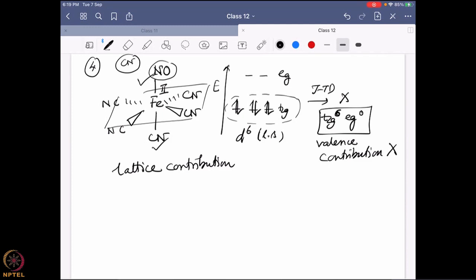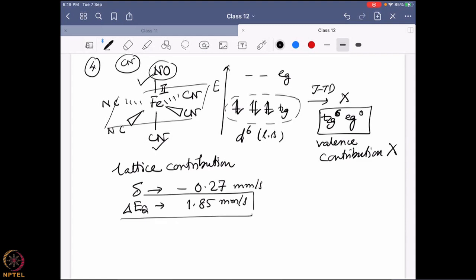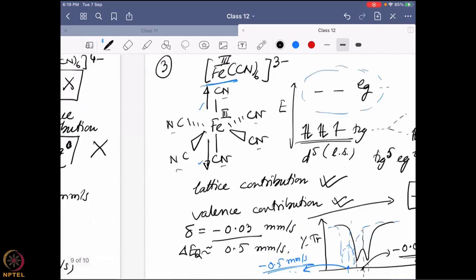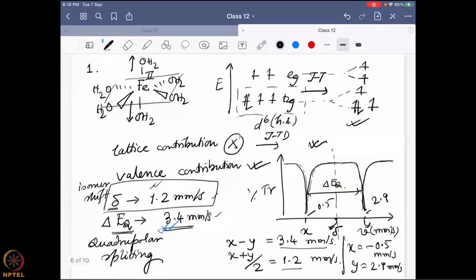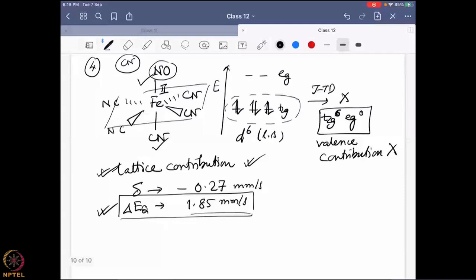And over here, what we are going to see is the following. The delta value is going to be minus 0.27 millimeter per second. And delta EQ value is going to be 1.85 millimeter per second, which shows that the delta EQ value you're seeing is coming from lattice contribution. There is no valence contribution, but lattice contribution is there. And look at this value, 1.85, compared to that water molecule bound system when both lattice and valence contribution were there, it was 3.4. Now one of them is cut off, the valence contribution is going out in the case of this complex, and that is why the delta EQ value is going down. So you can see it is kind of additive. More contribution you are getting from both lattice and valence, and it is going to be contributing over there.